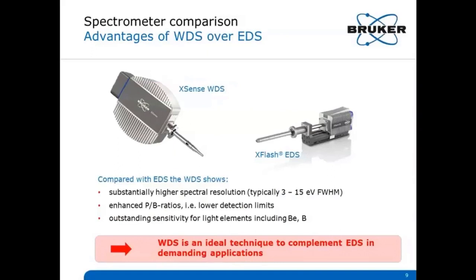Second, enhanced peak-to-background ratios, which translates into lower limits of detection, up to about 100 ppm. And third, this is a special property of the parallel beam spectrometer with the grazing incidence optic, outstanding light element sensitivity.